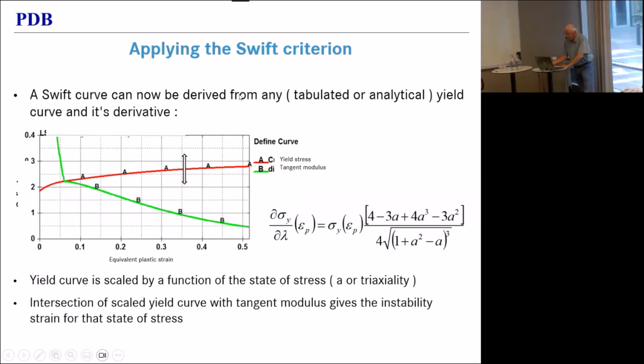Well, once you have that equation, you can use it. So given you have a yield curve for a certain material, that would be the blue curve. You take the derivative of it, so you derive that yield curve with respect to the equivalent plastic strain. That would give you the green curve. Wherever these two curves intersect, that is the strain at necking. That is the start of localization for a triaxiality of 1/3.